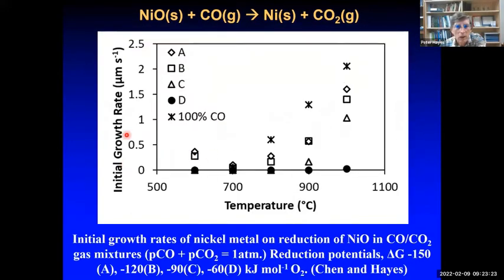Here you can see that growth rate as a function of temperature. And A, B, C, D are different thermodynamic driving forces. So 100% CO is the maximum driving force we can apply to the system. And A is getting close to the equilibrium between nickel and nickel oxide, so it's a low thermodynamic driving force. What we find is that the rates not only go through this minimum at somewhere around 700, but also depend on the thermodynamic driving force and the partial pressures of the reducing gas.